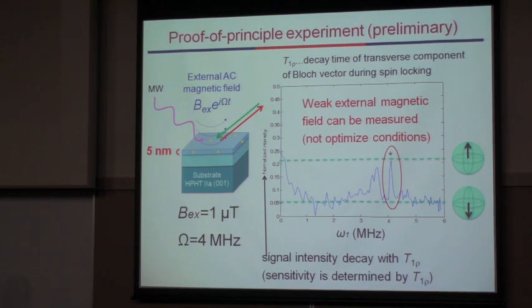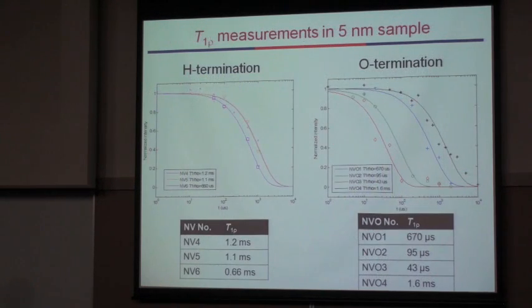So in order to estimate the performance of our magnetometry, we measured the T1rho in our sample. The T1rho is an important factor to determine the performance of this magnetometry. This T1rho corresponds to the decay time of the transverse component of the Bloch vector during spin locking. So this is a result, and we obtained a very long T1rho, which is of the order of millisecond in our sample.